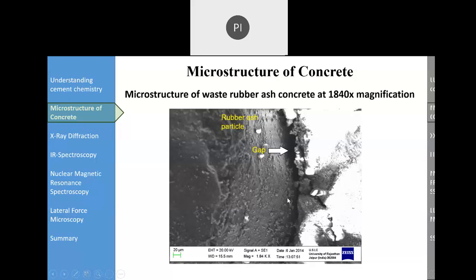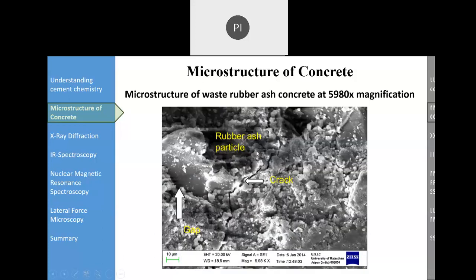So that means, not aggregate, basically this is cement paste, sorry. So there's a clearly visible gap between rubber ash particle and cement paste. That means that this interface is not good, and that means we will be getting lower strength. Here, in this rubber ash particle, we can even see the crack within the rubber ash particle also. So it also gives us a lot of information about how the durability properties and the mechanical properties will be affected due to this crack in the rubber ash particle.